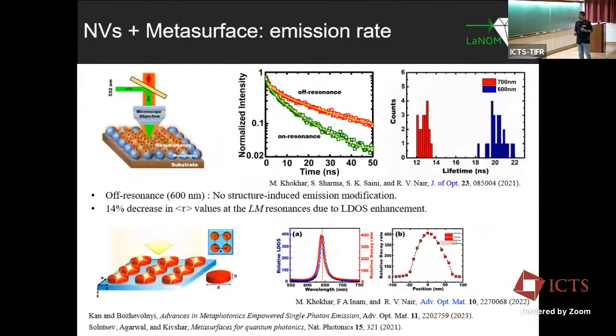So the student put NV centers on top, and we try to do the measurements. We see that off resonance the decay is a bit slow, but when you have on resonance, with the metasurface resonance matched, you get a very fast decay in the system. So by using simpler structures, we can engineer the light emission from the NV center. When we did a lot of measurements, these distributions are quite distinct.